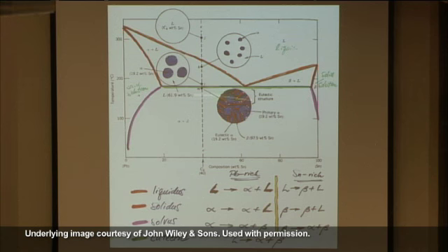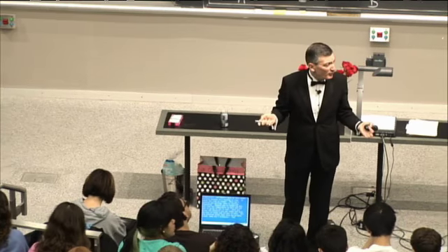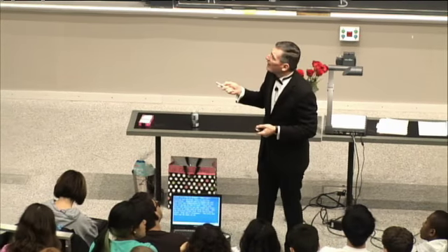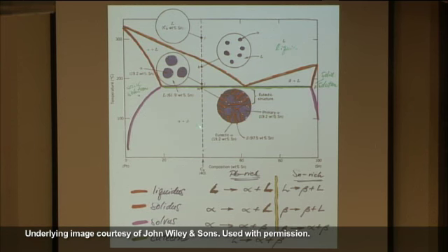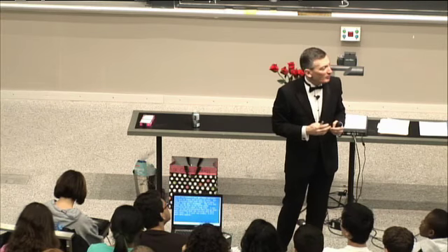Once you cross the eutectic temperature, now it's alpha plus beta. So now you get this lamellar structure, stripes of alpha, stripes of beta. But the previous blobs that formed the primary alpha, they don't disappear. The only way they can disappear is by solid state diffusion. That's going to take a long time. So I can look at the microstructure here, and I can go back and calculate what the cooling rate must have been. If I cool very slowly, I will have more nearly the equilibrium structure.